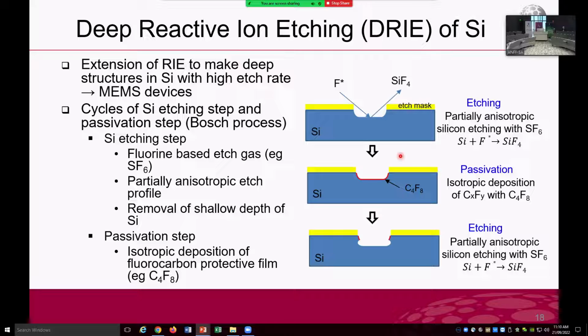Okay, now let me talk a little bit about deep reactive ion etching. This is the second implementation to achieve vertical sidewall profiles. It's about the sidewall passivation technique. In the first step, we can see this etch mask pattern, and this technique uses fluorine as etchant, because fluorine gives a very high etch rate. But the problem with fluorine is that the etch profile is partially isotropic. So you can't keep going with the chemical reaction with fluorine. If you keep going, you will end up getting this round etch profile. It's not completely isotropic, but it's a partially isotropic profile.